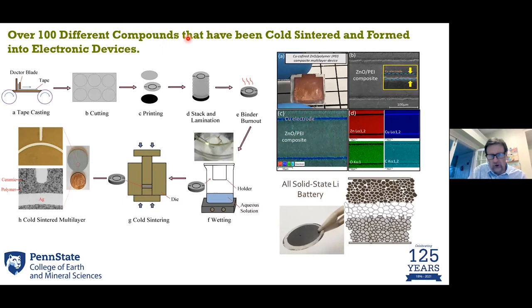We've done over 100 different compounds now, not just oxides, but a variety of different materials. And more than just densifying them as a ceramic, we've designed them in ways that we've even made electric devices and found processes to tape cast, stack, put electrodes in system to make devices. And over here, you can see multi-layered type devices for a varistor being made, where we're also not just co-sintering the ceramic, but also the metal electrodes, all within this same process. And I think this work was done at 150. And we're also looking at how to assemble new solid state batteries with this same type of technology.